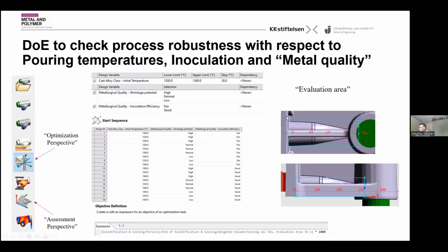So what I then did in the geometry perspective, or in the CAD part of the program, I just included a small box. And that box is what I call an evaluation area. My objective is to reduce the porosity within this volume inside the part. So I can say that at the end of solidification, I want to have my weighted volume, which is basically the total pore area inside the casting, which is also inside my evaluation area. This will be a result telling me the pore size in cubic millimeters in this volume and how that is affected by these parameter changes.